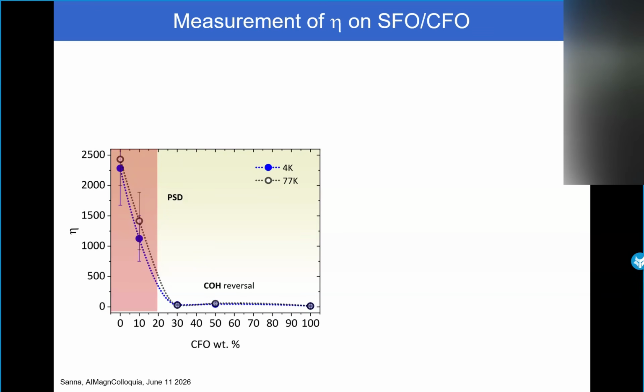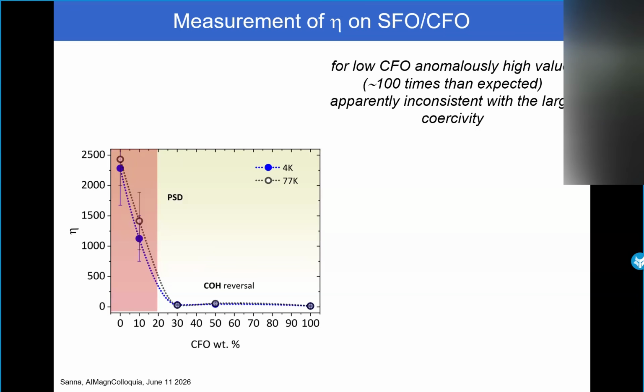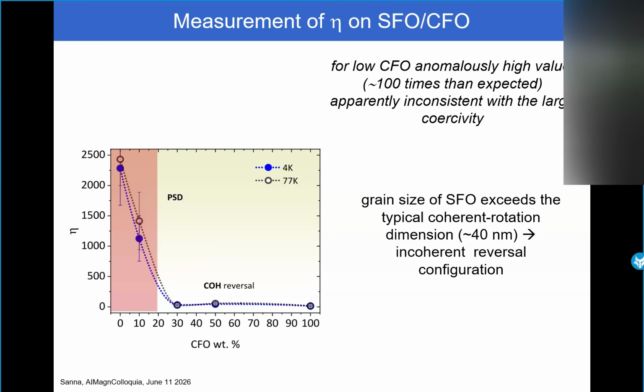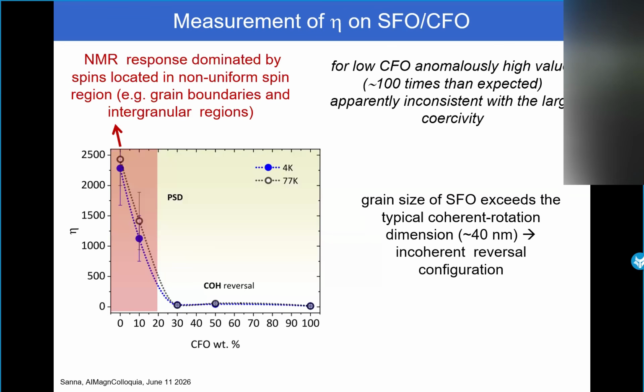Because this is a relatively hard material. And so this is because for low CFO content, we have this very anomalous increase that we didn't expect, apparently inconsistent with the large coercivity of these materials. Then we had to consider also that there is a grain size effect in relation to the coherent magnetic volume of the system, which is typically this threshold size.